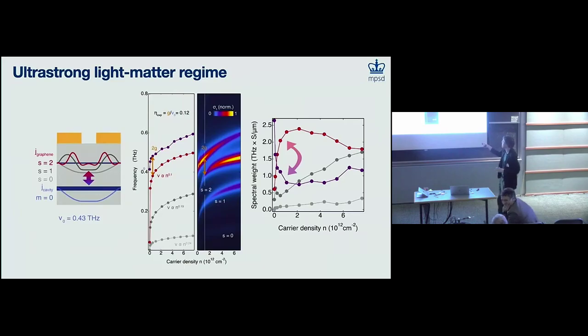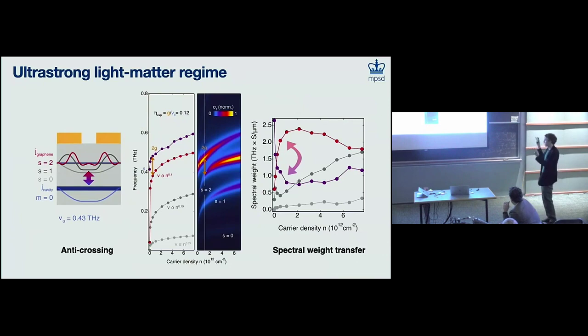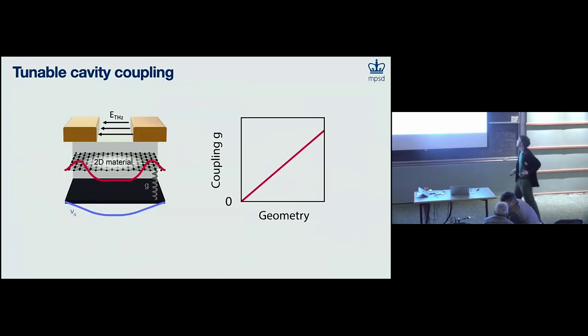This is what most clearly shows this is the result of Marios' simulation. Here you can see the avoided crossing forming, which agrees with our data. You can also see the spectral weight going from this mode to this mode, which is consistent with the data that we see here. And so we see these two signatures, this anti-crossing and the spectral weight transfer, in this device.